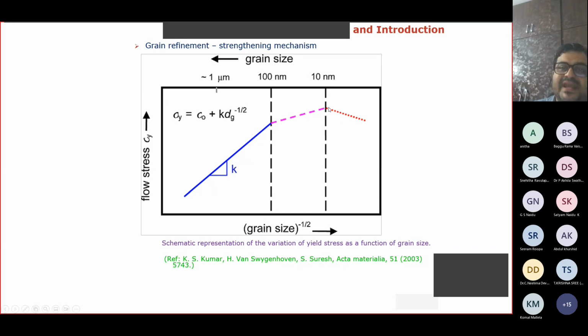And again, when you decrease the grain size further below 10 nanometers, you see that you have a negative slope here, that is minus K. This red dotted line shows the negative slope minus K. That regime is called the inverse Hall-Petch effect.